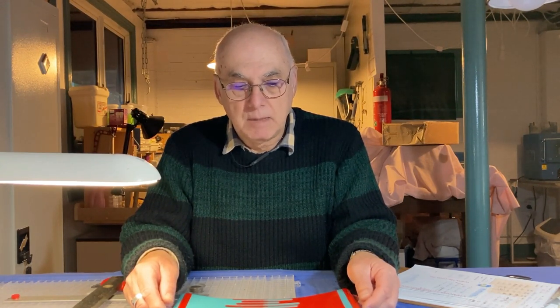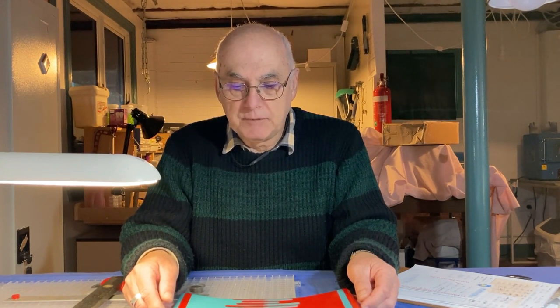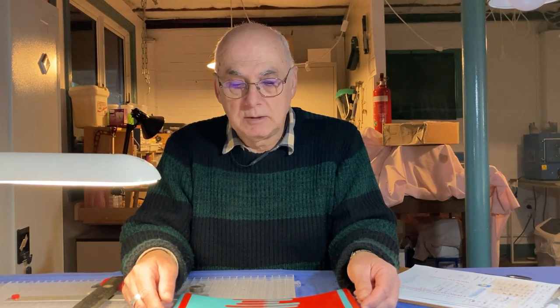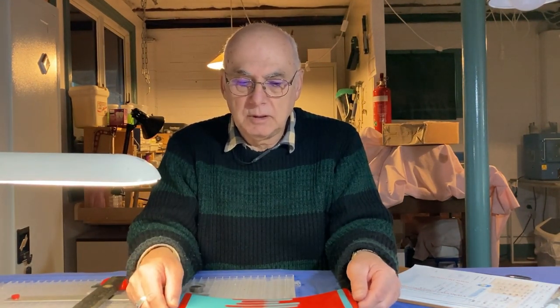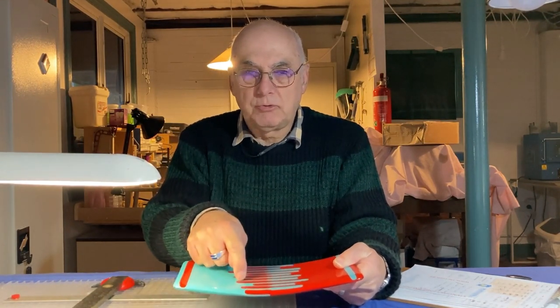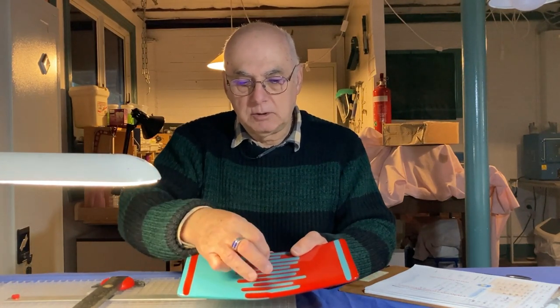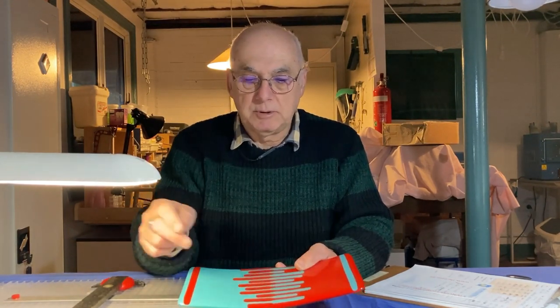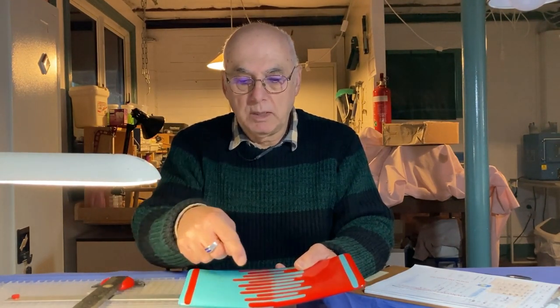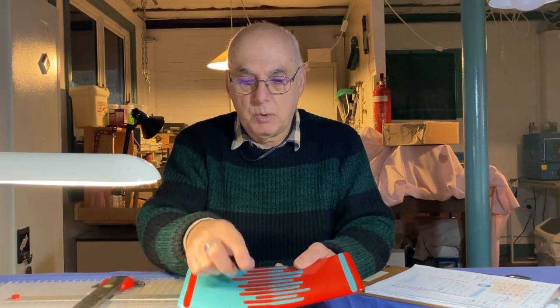I'm going to ask you a question. Is it turquoise on red or red on turquoise? In fact it's actually both but visually it would confuse you a little bit. Some people will take it one way, others will take it the other way, but it makes it a really interesting piece. Something that puzzled me at first but I think I do understand why now is why do we actually end up with paddle shapes? When you think about it a bit it's not hard to work out. You will remember that we laid up strips of turquoise, strips of red, but in the middle they were up against each other so that didn't allow them in the middle here to spread out. Whereas where it extended out here and out here that allowed it to spread out over the base piece. And so we ended up with that paddle shape where we got a narrow end on one side and the wider paddle shape on the other side.